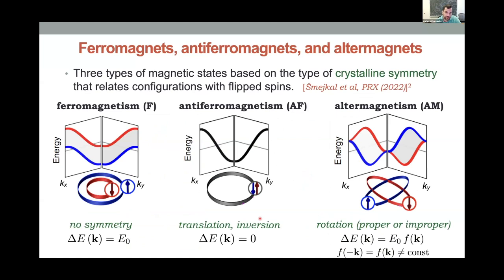And so if you want a brief summary, you have three classes of magnetic ground states. And again, it depends on which symmetry you combine with time reversal to get the system invariant. No symmetry is ferromagnetism. If it's translation, or actually if it's inversion, both work the same way, you get no splitting. And in altermagnetism, you get a rotation. And when I say rotation, it could be proper, improper. Most times it actually is combined with a half translation, so it's a non-symmorphic operation. The spin splitting acquires momentum dependence that is even in momentum.